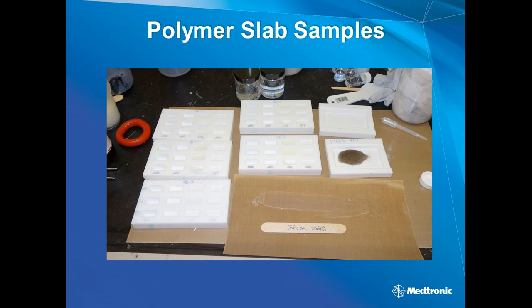They're not heat cured thermoset polymers, which is good because that was one of our fears initially, that if you had hot curing polymers, it might potentially destroy your irritant chemicals. So that hasn't been an issue with these, and we've run a lot of range finding studies to figure out how much you have to put into a polymer in order to get out enough when you run an extraction on it to fail this test.